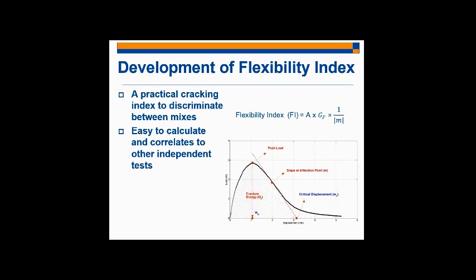And so then we added this factor of A, which basically just makes the results of the flexibility index look nice. This can be a factor of 1,000 that you divide by, or 100, or whatever is needed to make the results look nice. So this is the proposed flexibility index, just simply the fracture energy divided by the post-peak slope of the line fit to the first inflection point past the peak load. And we found that this index, as I mentioned, correlates to other independent tests, which I'll mention later.